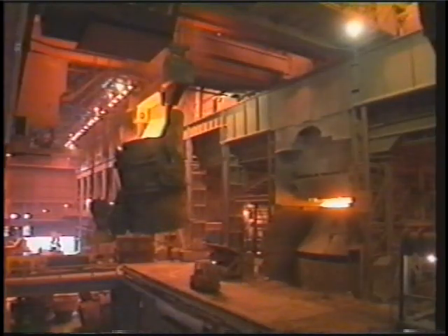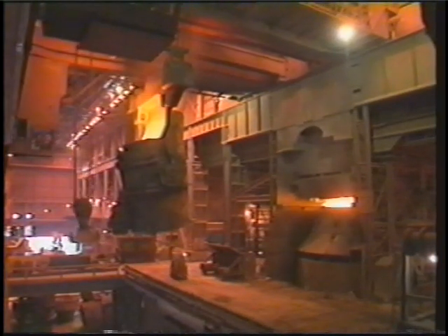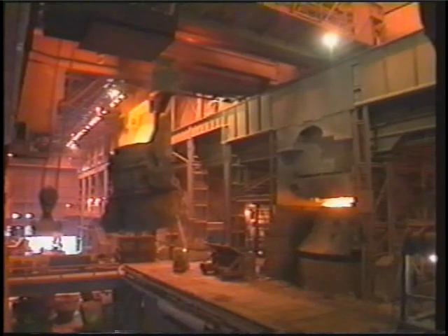The stirring action of the metal by the gas improves the mixing between the slag and metal interface, resulting in better uniformity of the bath. The mixing leads to better yields and improved cleanliness. The processing takes about 25 minutes.